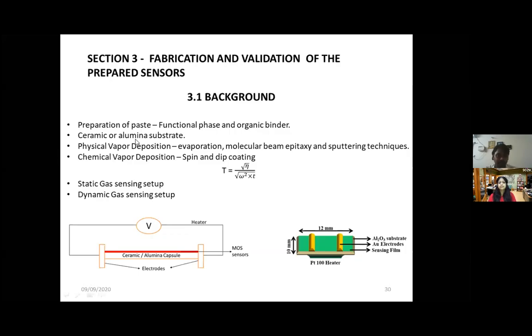Dip coating is nothing but dipping this alumina substrate into the paste. Spin coating is making this alumina substrate spin at a particular RPM and dropping the paste on the spinning substrate. The thickness of the coating can be optimized using this formula, where eta is the viscosity of the paste, omega is the angular velocity of the spinning substrate, and T is the duration of the spinning. So this is the schematic illustration of the sensor.